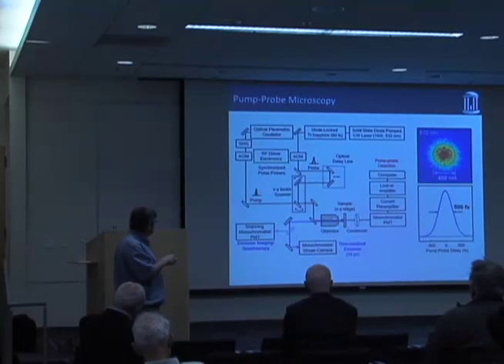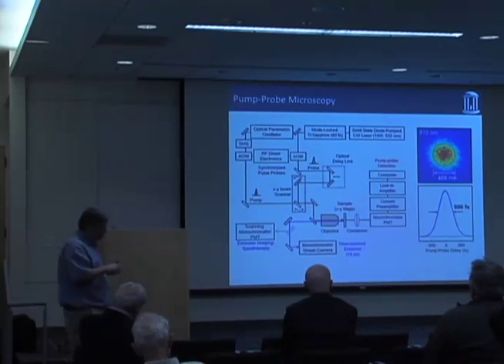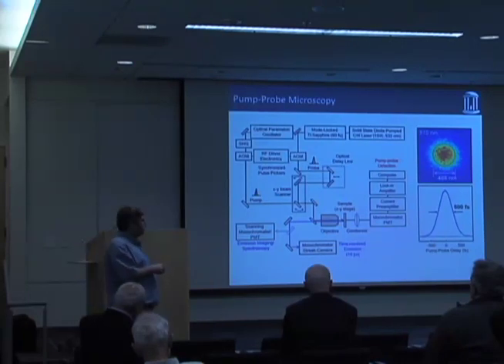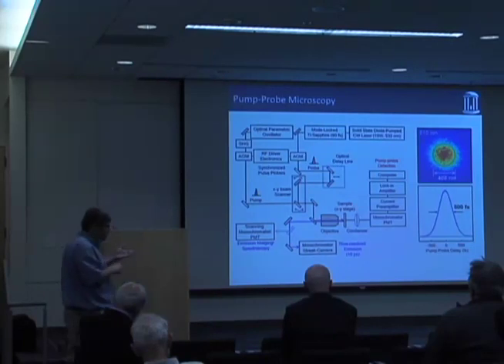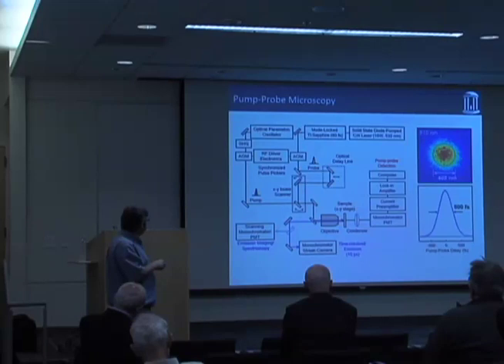We then take the probe beam, collect it after the sample, and do lock-in detection. Essentially the type of technique I'm going to tell you about today is transient absorption or transient transmission experiments, where we're looking at the change in intensity of the probe beam as a function of whether or not the pump is there, or how the intensity of the probe beam changes with the presence of the pump.